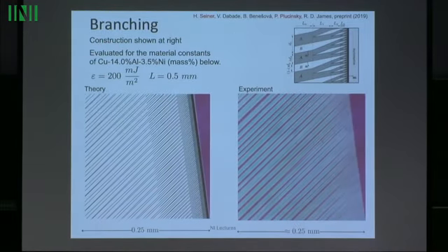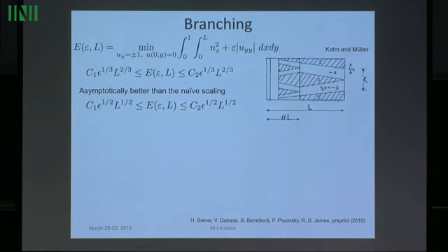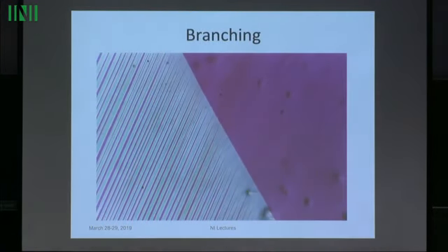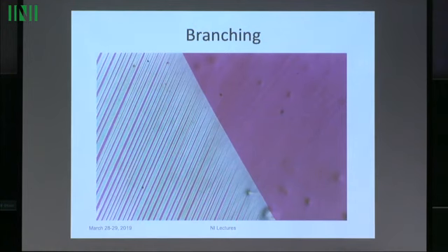And that's going to play an important role in hysteresis. Let me explain why. Imagine that you're, let's go back to maybe the more simple picture. There. So you imagine you're in the austenite phase. You're all red on your crystal. You're at high temperature and you're cooling the crystal, and you reach the transition temperature, this theta C, where the wells are at the same height, the austenite well and martensite. And now you're continuing cooling a bit, and so the martensite well is getting a bit lower.